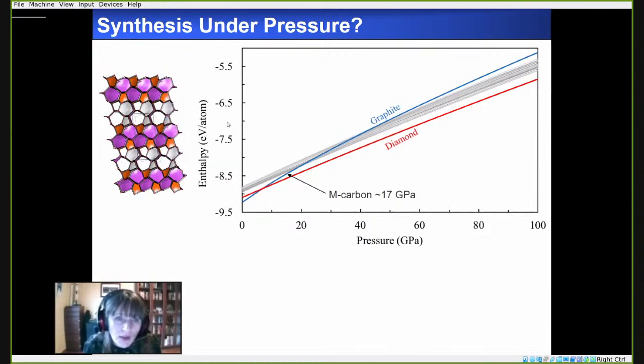Here I show a form of M-carbon, which was synthesized under pressure using the cold compression of graphite. And here I show the enthalpies of the calculated superhard phases versus pressure, and I compare them to diamond and to graphite. Note that by about 60 GPa, all of them are going to be more stable than compressed graphite, suggesting that many of these phases could potentially be synthesized given the correct precursor materials and synthesis protocol.